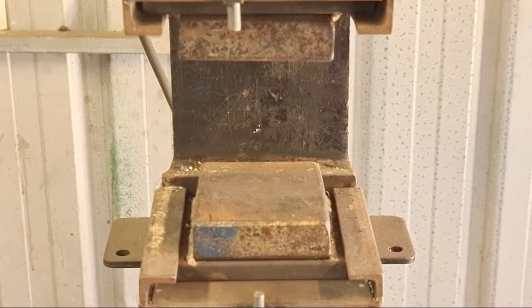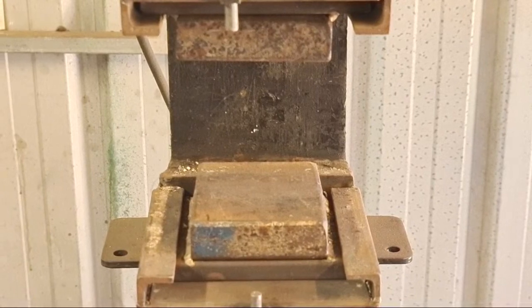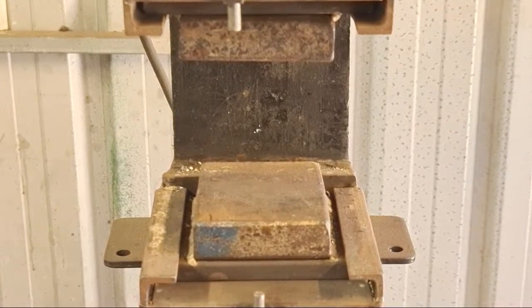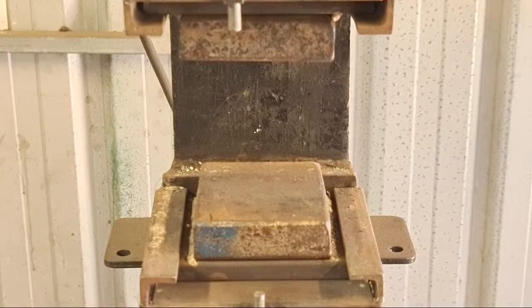You didn't order the O1? Oh no. Yeah, so you can go from a medium or a high-speed quench oil on 1080 and get a decent hamon if you use clay. Same with 1075, same with 1085, 1084. 1084 is a little bit different because it's got a very high manganese content, so you won't get a lot of activity out of the hamon, but you will get a hamon, as I've proven, because I've made one on 1084 before.